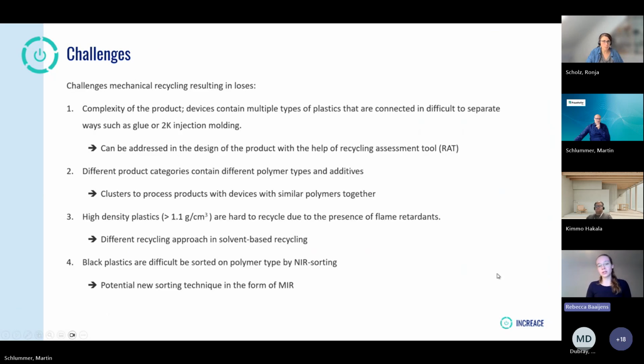Then, of course, we already had some main challenges, but then specifically looking at mechanical recycling. And mechanical recycling here is both the pre-processing as we do at Mirex, so that's up to the point of the bigger flakes. And then also the problems of mechanical recycling after us that really go from the big flakes to something that the producer can use. Martin already mentioned it, but the complexity of products, both in the number and type of plastic used, but also all the other materials and typically how they are connected. Like if you have 2K injection molding, there's no way we're getting that separate. But also if things are glued, which means that if plastic or metals are glued together, it also becomes a lot harder to separate and properly sort them.